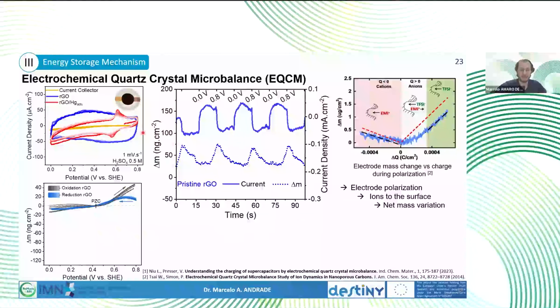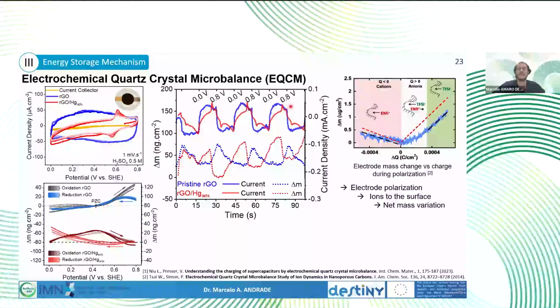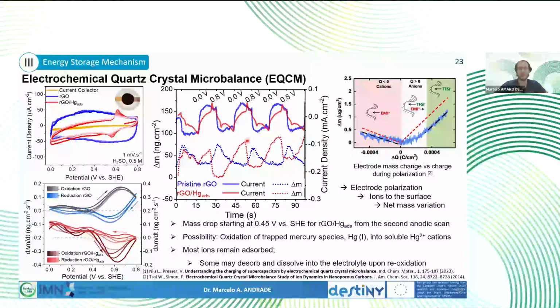Now, with the presence of mercury, we see in electrochemistry the redox peaks that we expected. Now with the electrode coated with RGO containing mercury, the mass variation starts the same way, but then when it reaches the first oxidation peak of the mercury, we see a very sharp mass decrease that corresponds exactly to the oxidation peak. And that happens repeatedly. So there is a reversible mass decrease and then increase from RGO containing mercury that was seen in EQCM. That mass drop is associated to the oxidation of these mercury species into soluble, possibly mercury 2+.